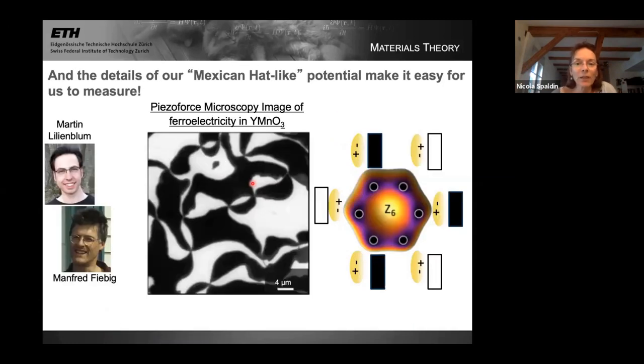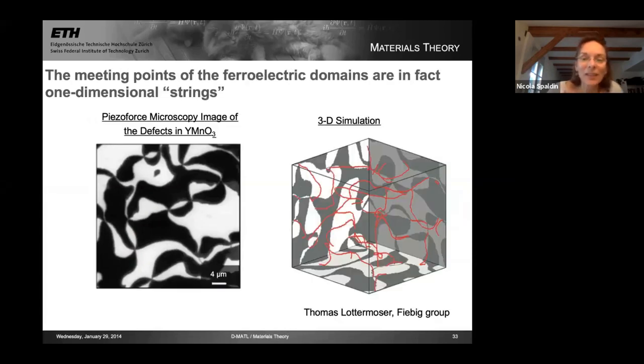So here's what one gets when one does that. I shouldn't say these are simple measurements. These are extremely delicate piezo force microscopy measurements. These were done by the former PhD student of Manfred Fiebig, Martin Lilienblum. And again, you see as you go around one of the topological defects, the up, down, up, down, up, down ferroelectric dipoles corresponding to moving around these six minima in the hat.